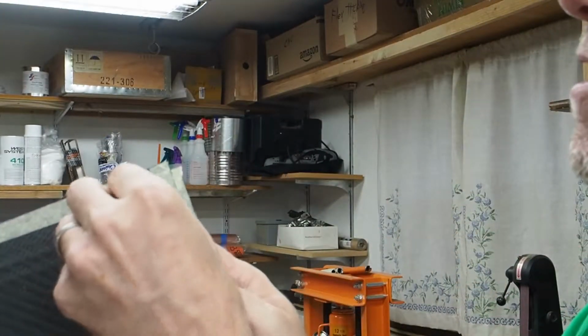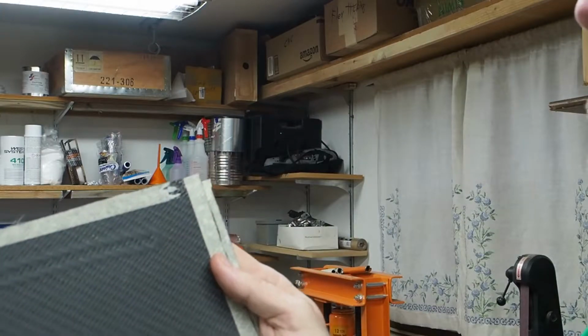Another thing that I checked is some masking tape that actually went through the epoxy curing process under vacuum. This is my second attempt at vacuum infusion, and it was a failure, but I learned a little bit more, so we're making a little progress on that. But let me show you where I put the tape on to cut the carbon fiber along the edges. I am able to peel off the tape. Now it comes off in pieces, but I am able to remove it, which means that the epoxy did not soak into the masking tape and it did not dissolve the adhesive on the back side.